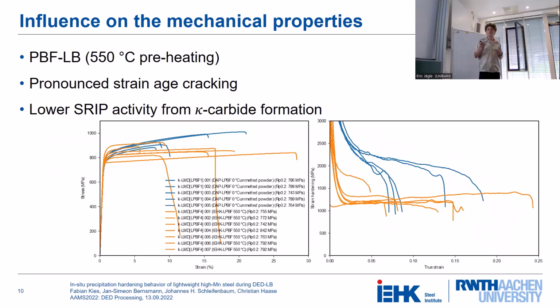And even though the properties are very scattered in tensile testing, so here you can see you have a lot of scattering of the elongation due to strain age cracking, but still, what you can see here, the blue curve is without preheating and the orange curves are with preheating. If you take a look at the strain hardening rate, you can see that the strain hardening is much higher in the samples without preheating than in the samples with preheating. And this is again a result of the formation of kappa-carbides, because they inhibit the SRIP effect during deformation, and therefore the strain hardening rate goes down.